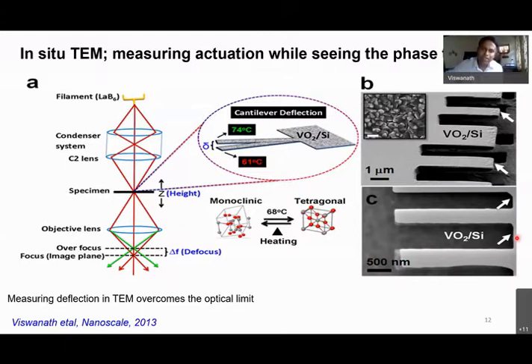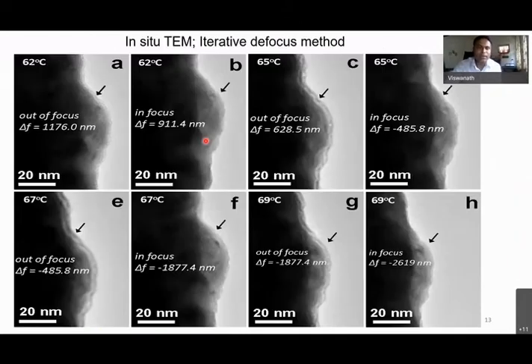Again, rise to the next temperature, iteratively, and measure the defocus value. So at the end of the experiment, we'll have the defocus value and how it is changing as a function of temperature. The same experiment I can do for the tip as well as for the base. Any cantilever, of course, when it is clamped, you will not expect any deflection there. So the difference ultimately will give you the actual total cantilever tip displacement. So that is what's shown here.